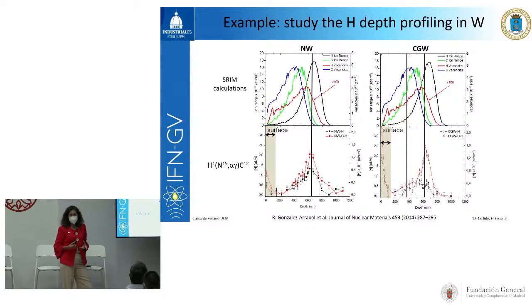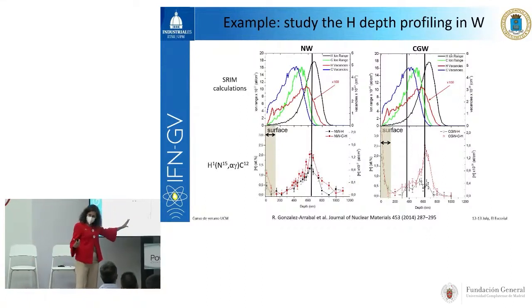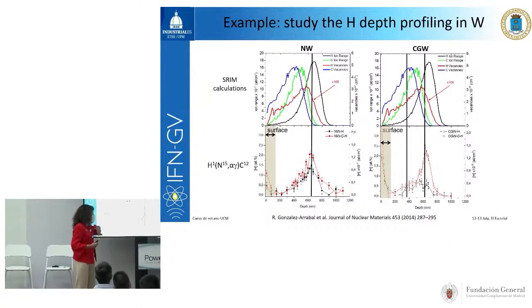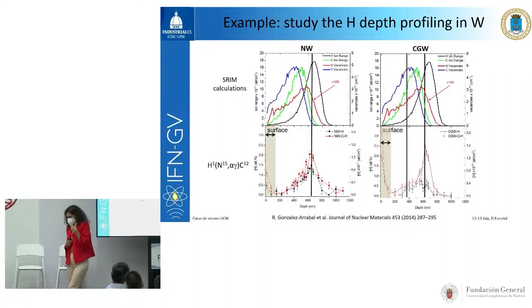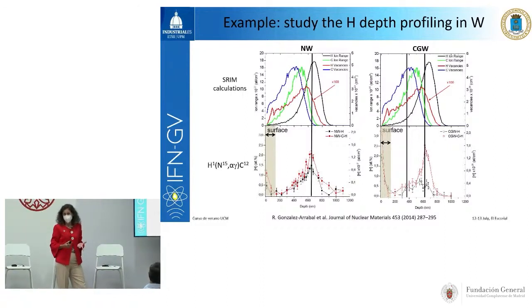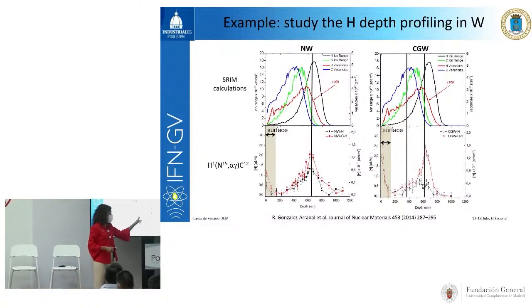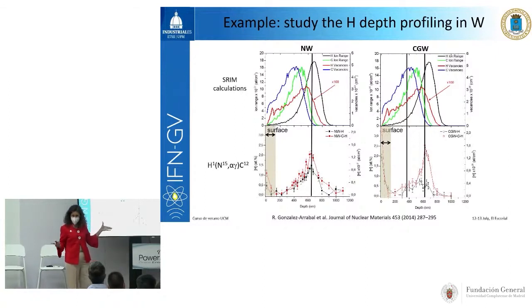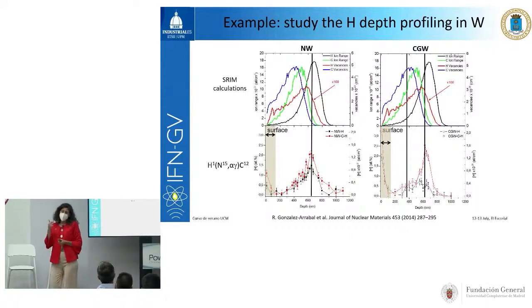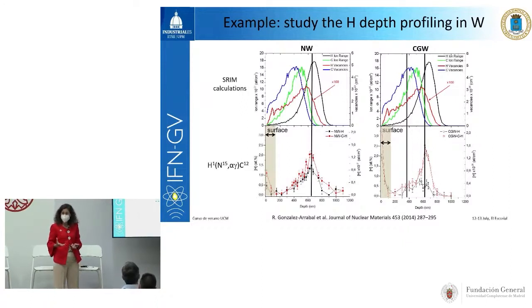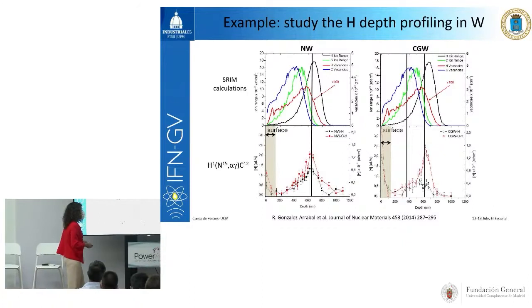So what we have to do is go to computer simulations, and I have to say that this is really a very important point. As far as we can, we have to perform computer simulations and experiments: computer simulations to really understand the results of the experiments, and experiments to corroborate that the computer simulations are done in a proper way. In this particular case, what we observe out of the multi-scale computer simulations, starting from DFT, molecular dynamics and object kinetic Monte Carlo, is that in the nanostructured samples we are creating a large density of vacancies where the hydrogen is accumulated.